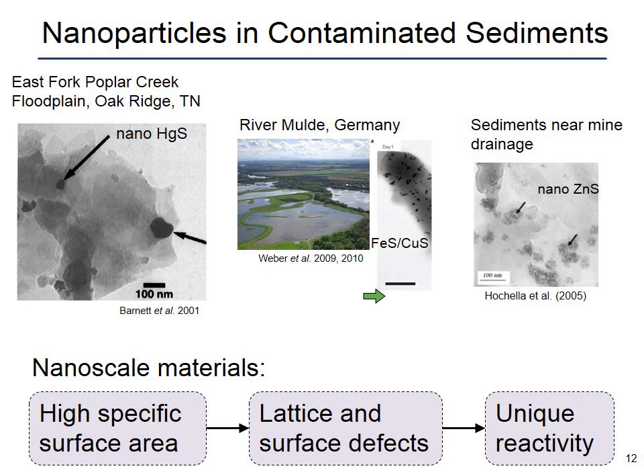And I want to distinguish between nanoscale materials and what we conventionally call colloids, because nanoscale materials are nanostructured, not necessarily nanoparticles in size in terms of being less than 100 nanometers, but they're actually nanostructured. What that means is that they have a high specific surface area, which also lends to defects on the surface of the particles, as well as lattice defects, and this gives the particle reactivity that's different from what you would observe for bulk scale materials, materials that are not nanocrystalline.